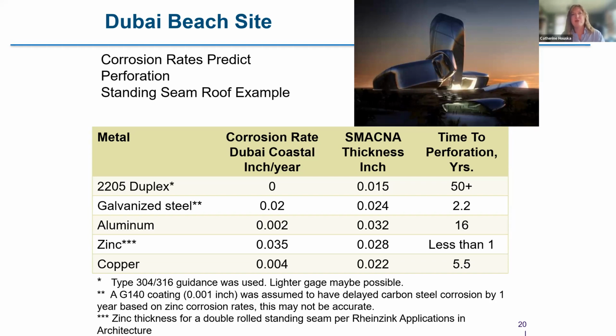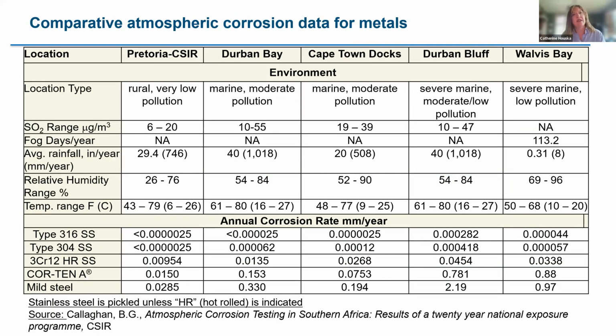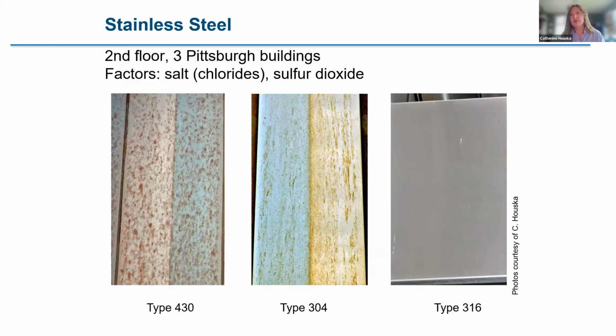In comparison, everything else corroded at a very rapid rate, with aluminum having the next best time to perforation at 16 years. So there is data from South African data, and you can see this here. I'm comparing more materials. If you look at Durban Bay and Walvis Bay, which are the most aggressive marine environments, you can see 316 and 304 versus weathering steel and mild steel. And there's a huge difference in corrosion rate in a more aggressive location. So there is data to assist with these decisions.